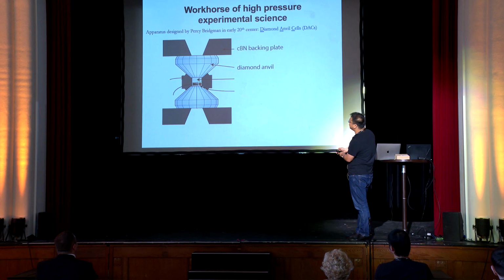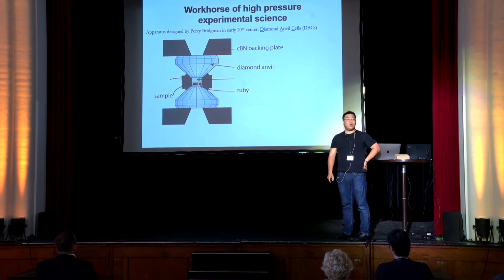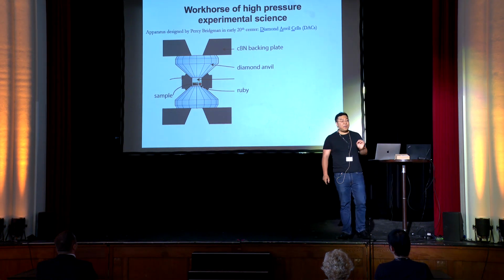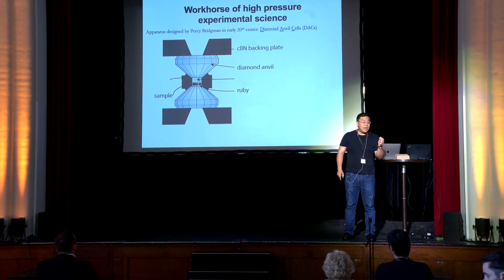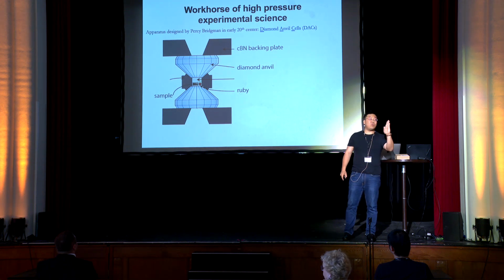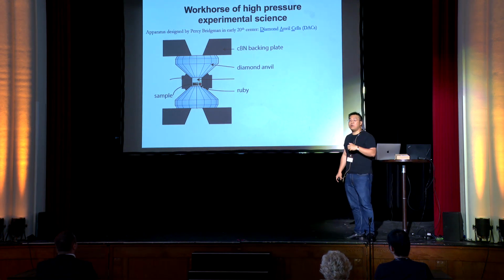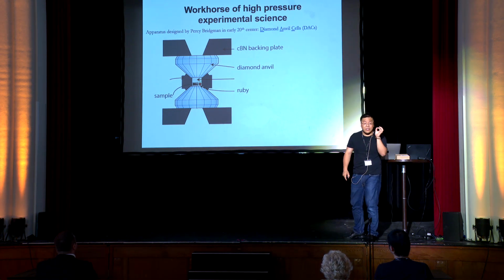The two anvils here, then you can see, naturally define something like a sample chamber inside of them. Inside that sample chamber, typically one puts whatever samples one's interested in, but also one puts a little chunk of ruby, and that's because ruby acts as a pressure calibrant. So the photoluminescence of ruby is extremely well calibrated under pressure, so most oftentimes in many of these experiments you'll see a little chunk of ruby.